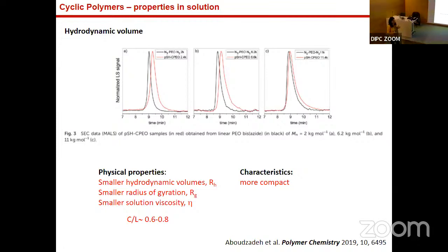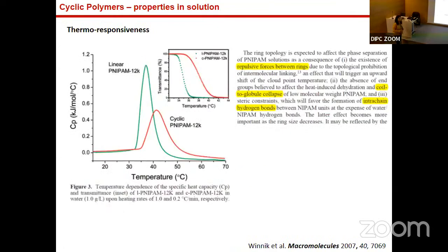to 0.8. These characteristics allow us to characterize the cyclic polymers by size exclusion chromatography or gel permeation chromatography. If they have the same molecular weight, they will elute later in the chromatogram. And this allows us to say, okay, we got the cyclic polymer after the synthesis. And this happened at different molecular weights. This is a result obtained by Ali some years ago with some kind of polymer, and I present it here as an example of hydrodynamic volume.